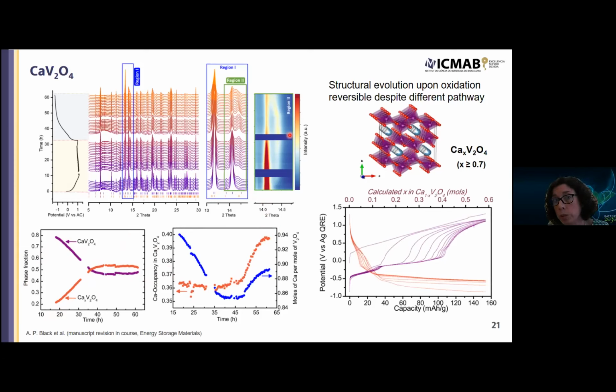So we did some attempts to build cells which would attempt to cycle in different conditions. The profile does change upon cycling, and of course, again, there is a lot of electrolyte oxidation, so it's something that we are looking at more closely, and there is still room for improvement, but at least this is the first time that we have shown that calcium can be extracted and reintercalated in the crystal structure of an oxide compound.